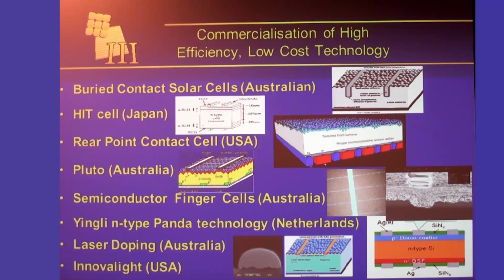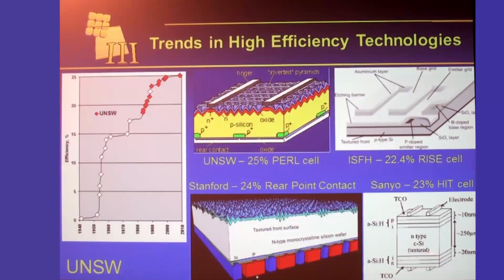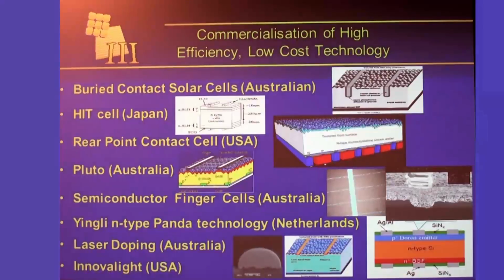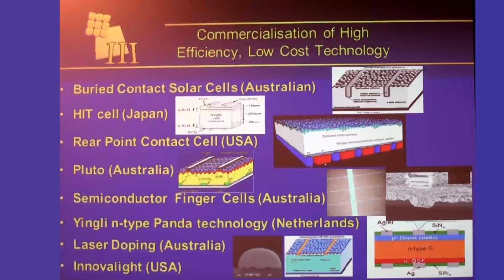A fourth one that I'd like to mention is the Yingli technology here, the Panda technology. It's actually, it's happened again. So the Yingli technology is actually, again, based on this cell design, but they've done it with N-type wafers. So they use a boron emitter, and you can see the cell structure here is basically the same as this cell structure here. And Yingli got that technology from ECN in the Netherlands. And Yingli's done a very good job at commercialising that technology and are getting somewhere in the range of 19.5 or even a little bit above.